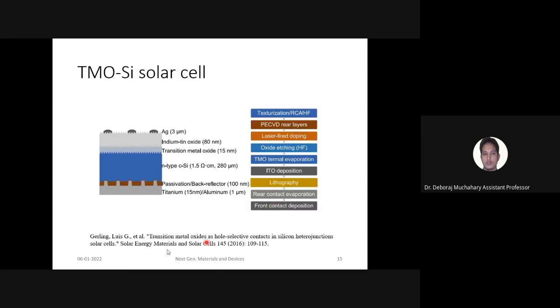Now, we can see a simple example of work done by Gerling et al. This is a simple schematic of the solar cell that is based on this hybrid TMO silicon solar cell, that is transition metal oxide silicon solar cell. Here in this structure, the main absorber layer is in the middle, and the light will be falling from the top because this is the front surface. The middle layer is n-type crystalline silicon. It has properties like a resistivity of 1.5 ohm centimeter, and its thickness is around 280 micrometer.